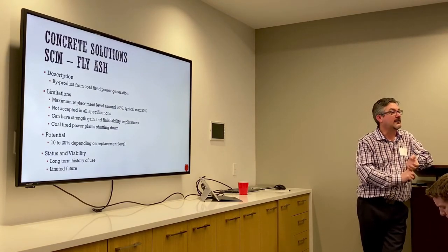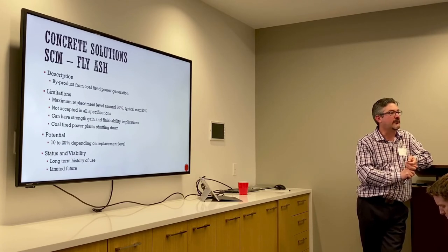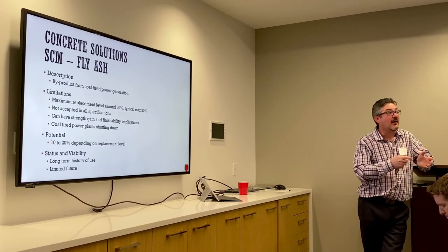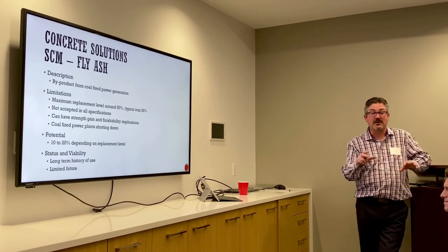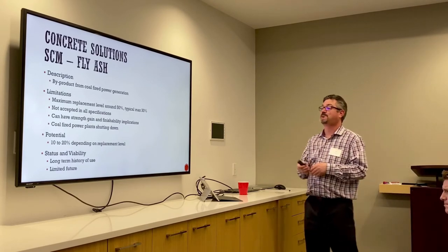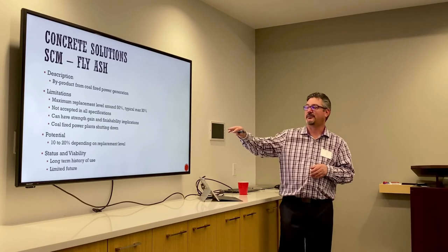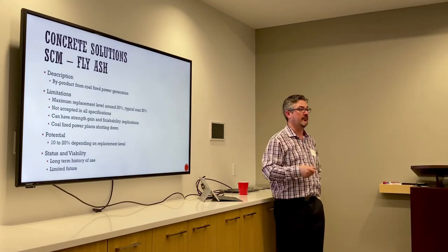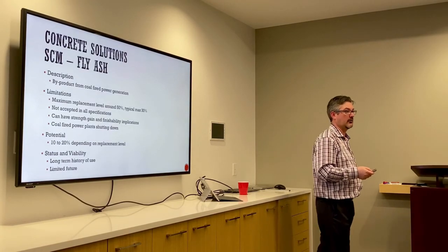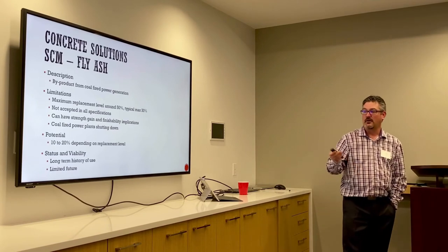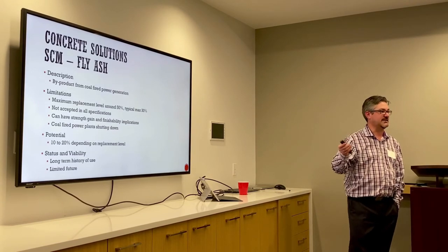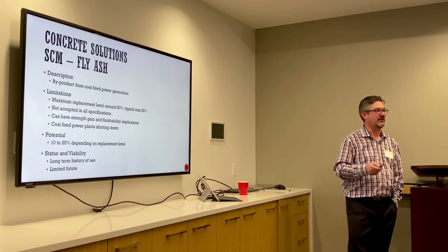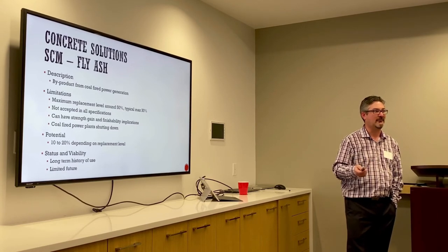Unfortunately, the coal-fired power plants are being shut down, so the lifespan for this is a bit limited. Depending on replacement level, somewhere between 10 and 20% CO2 reduction on a concrete basis. There is a long-term history of use, but as I said, these power plants are being shut down, so how viable it is long-term?